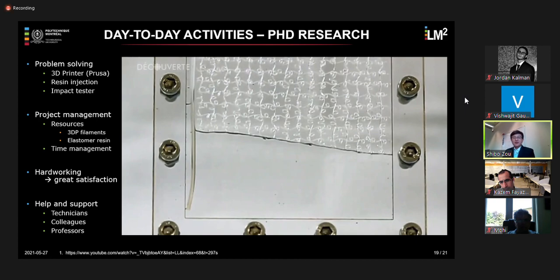But in the end, even though I was able to produce a high refractive index elastomer, the process is not scalable at all. I can only make the elastomer with a thickness of a few microns, and it's impossible to use that method to make bulk elastomer resin to form my composite. While waiting for the elastomer, I could have continued the project without the high refractive index elastomer, just using normal elastomer, and invested time in building up the impact tester and designing and carrying out all different kinds of impact tests. But it already happened. So that's the lesson that I wish I knew before the end of my PhD project.